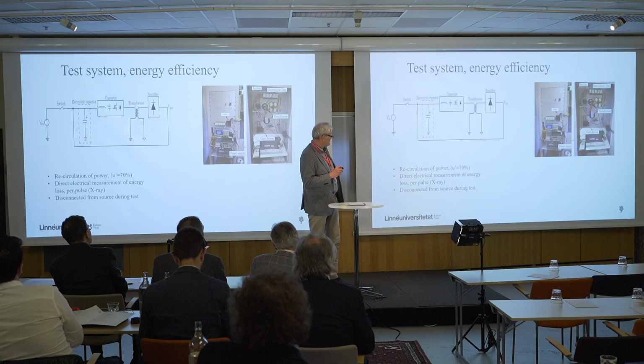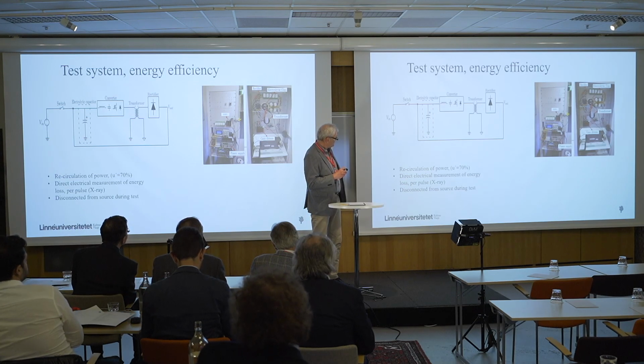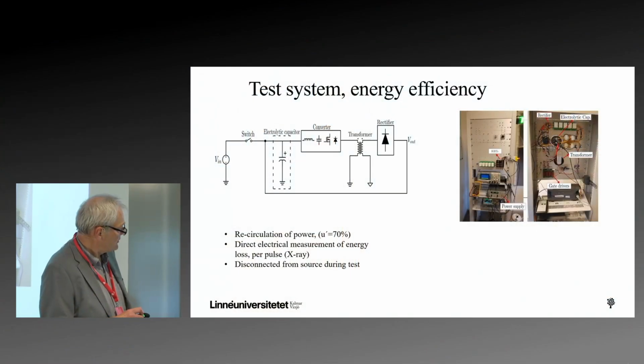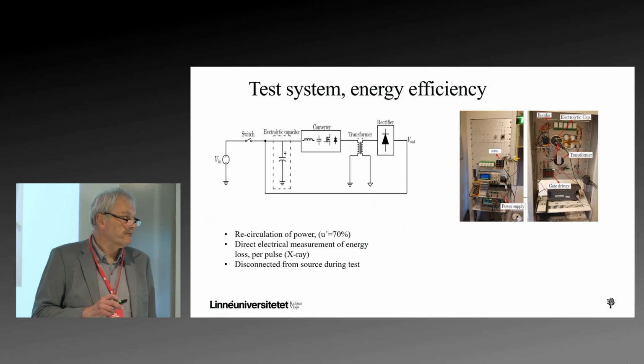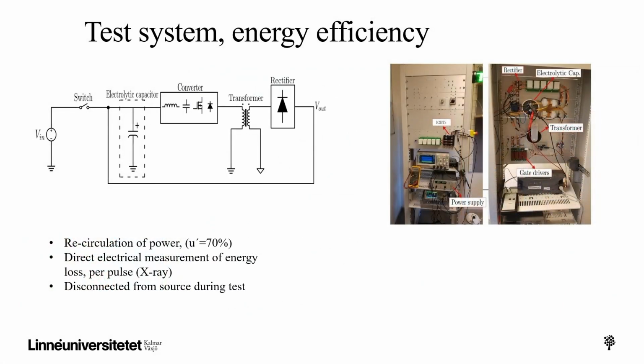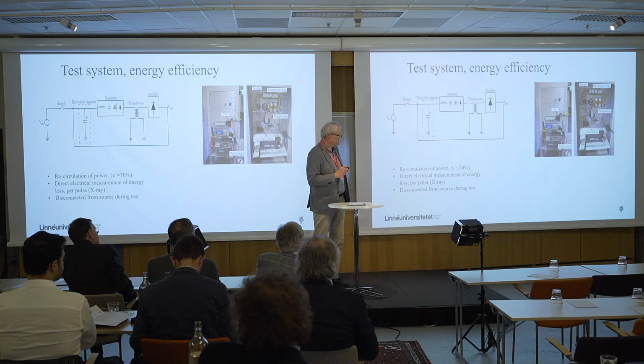So what we did here is that we built the system here, like what I showed in the main circuit diagram, with the difference that we don't have a high voltage transformer here. It's a transformer with a turns ratio between primary and secondary of roughly 0.7. That means that if you have 200 volts here, you will have 140 volts here. So the circuit will see 70% of the output voltage. And that is quite typical for this 100 kV pulse.